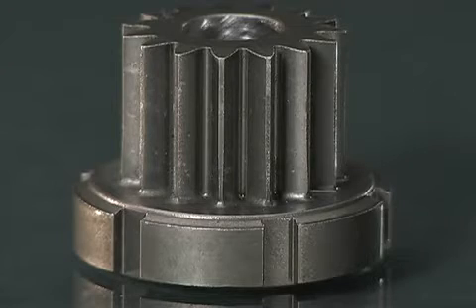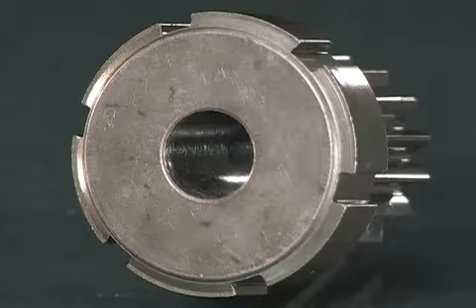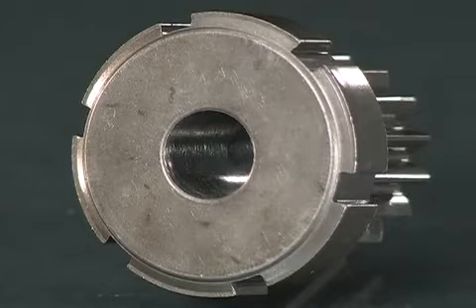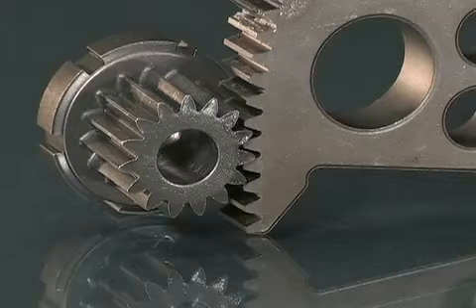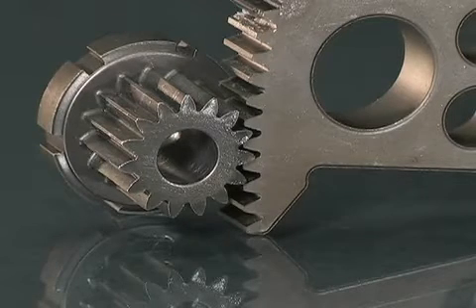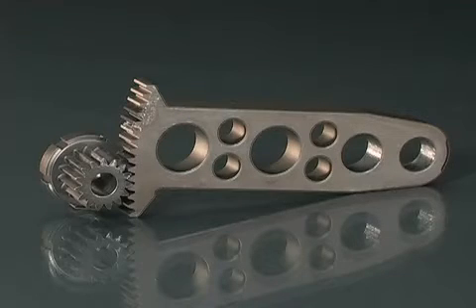The pinion gear, which meets the AGMA Q9 precision level, is selectively roll densified and crowned for bending fatigue resistance and rolling contact fatigue resistance. Both parts are hardened for wear resistance. Capstan's proprietary high-strength PM process and gear crowning design provided parts with twice the in-service life of those made via the previous manufacturing process and eliminated field failures due to tooth breakage experienced by those previous components.